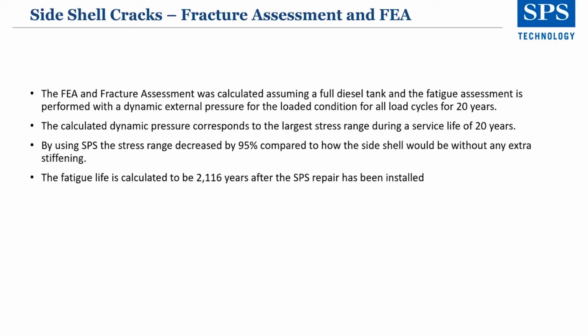With the fracture assessment and FEA, we calculated assuming that the diesel tank where the cracks were was full, and the fatigue assessment was performed with dynamic external pressure for the loaded condition of load cycles for 20 years. The calculated dynamic pressure corresponds to the large stress range during the service life, 20 years. By using SPS, the stress range decreased by 95% compared to how the side shell would be without any stiffening. The fatigue life is calculated to be 2,116 years after the SPS repair has been installed.